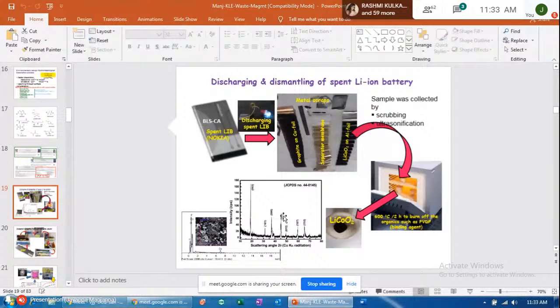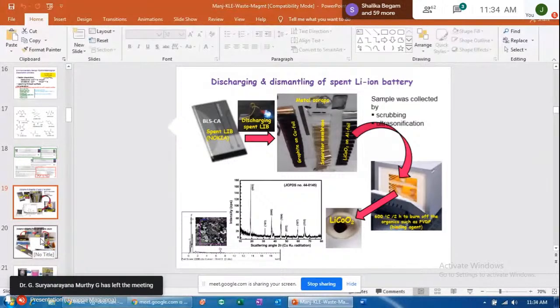Then we take X-ray diffraction and elemental analysis of that. Before treating any waste, we should know what those elemental contents are, isn't it? There are varieties of methods to know the elemental composition of this material. You do something called X-ray fluorescence spectroscopy, so there you can know the elements. So EDX, energy dispersive X-ray, and from that, with a backscattered electron image, you know the composition. Also simply, dissolve it and put it in atomic absorption spectroscopy or ICP-OES, so several. Also, from the materials, some pre-knowledge will be there of what kind of materials are present. Accordingly, you can test all of them and then treat.